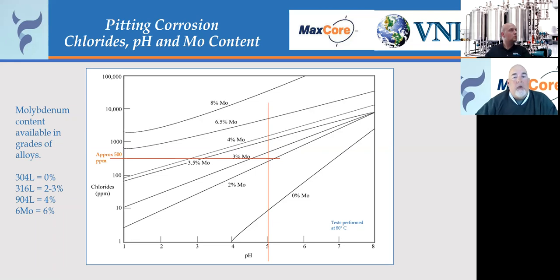If you look at that same pH of 5 and you look at a 6 moly alloy with a 6% molybdenum content, you'll see that now you can withstand about 6,000 parts per million of chlorides. So you can see that the molybdenum content itself plays a huge part in the resistance when it comes to pitting, and that's what it's designed to do.